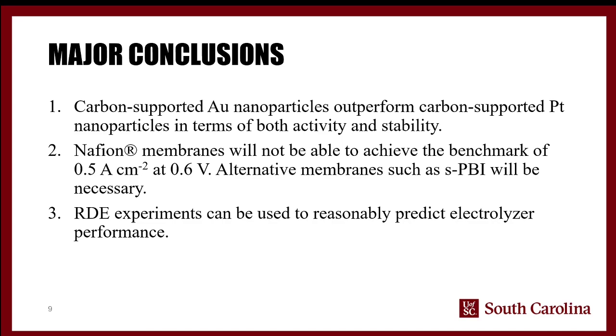So what we're going to have to do is look at some alternative membranes, such as sulfonated polybenzimidazole. I'll talk a little bit about that as well. You're going to have to switch to something like that that can handle both high acid and high temperature environments to hit the benchmark that you're aiming for. Thirdly, you can actually use rotating disc electrode experiments to reasonably predict electrolyzer performance. You may not know exactly how well it's going to do, but if you need to compare two catalysts or two preparation methods or something like that, you can use RDE experiments to have an idea of what you should expect, and you can use it to eliminate certain materials.